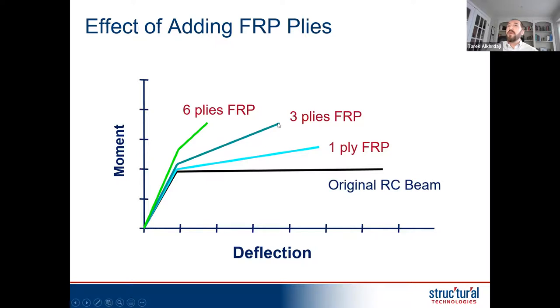But then at some point I find if I go 4, 5, 6, I hit a plateau in here. I'm not really exceeding the strength no matter what I do. So what's going on? At this point, if you keep adding tension reinforcement in bending, at some point you cannot increase the capacity because that interface between the FRP and the concrete has reached its limit. So it starts shearing off, and that is the debonding failure mode. It doesn't matter how much more FRP, your concrete at the surface reached its limit.